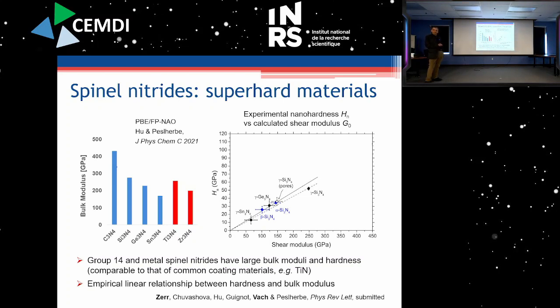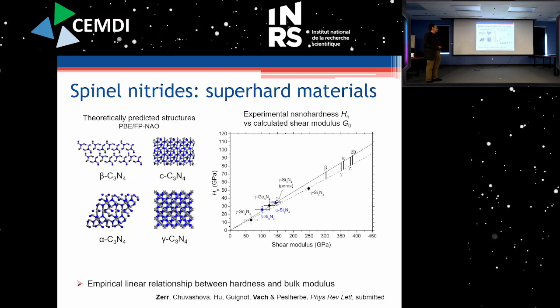And we could exploit this relationship or extrapolate this so that we could evaluate the nano hardness or predict the nano hardness of theoretically predicted phases of carbon nitrides. Okay, so these have not been observed experimentally, only the zinc blende one. And so from extrapolation of the calculated bulk moduli for those theoretically predicted structures, we find a nano hardness in this range here, about 90 to 70 gigapascal.